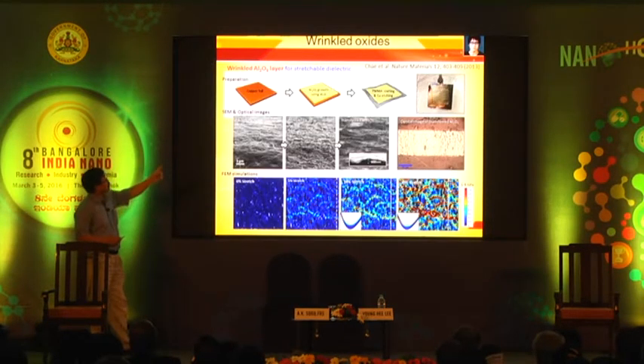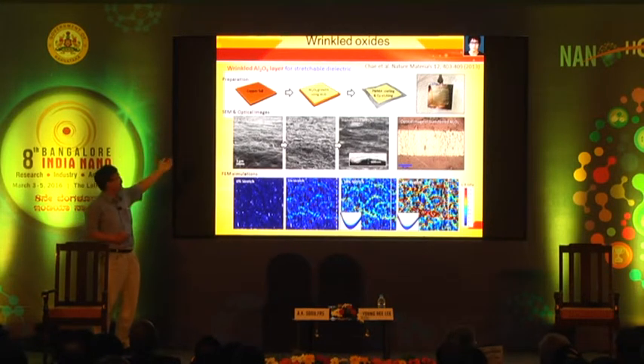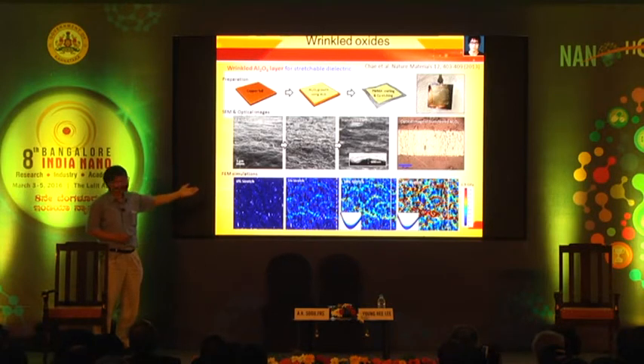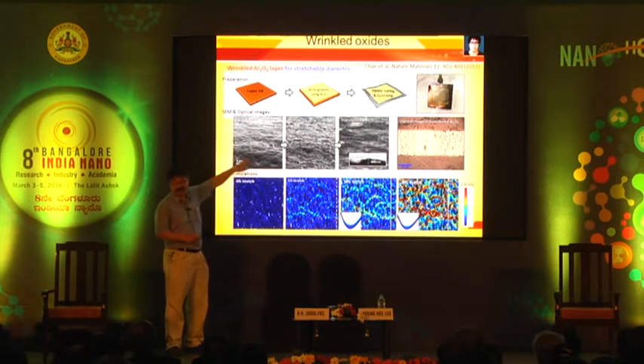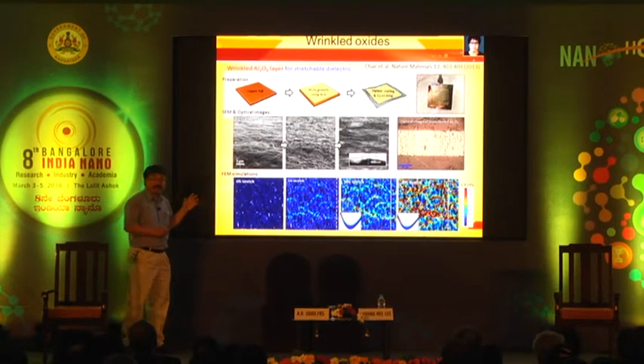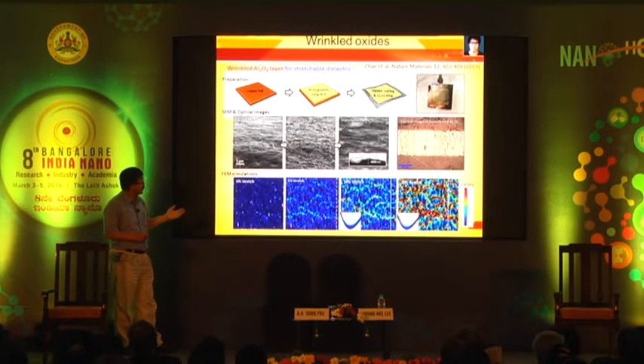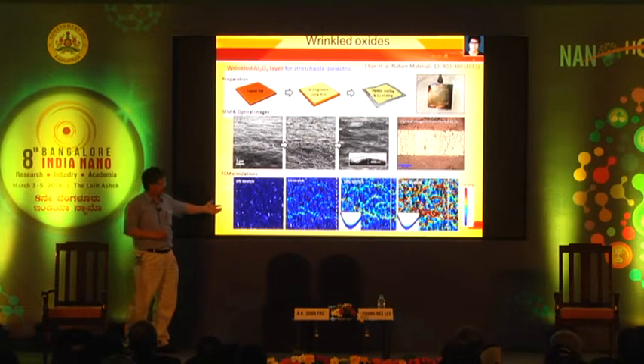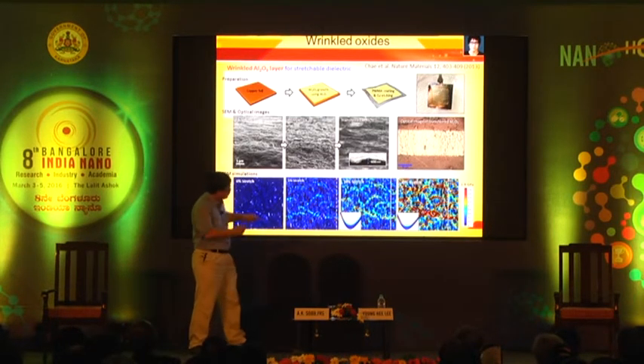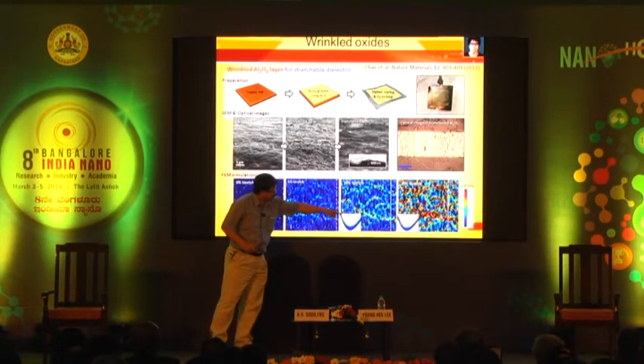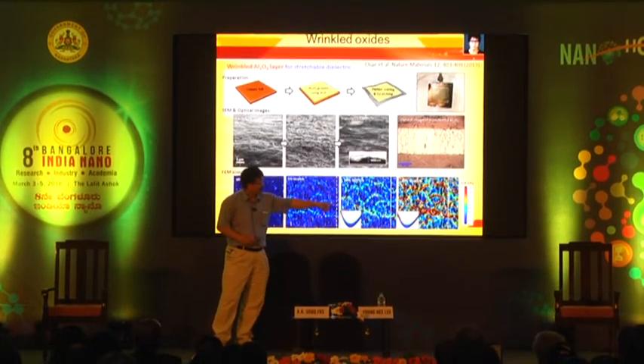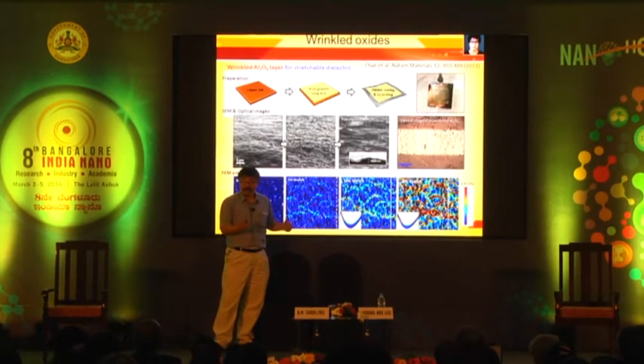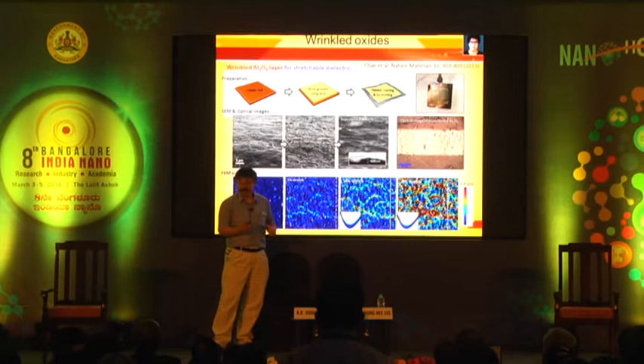So this is the method. We have a copper foil, and we simply deposit aluminum oxide using ALD. Then we deposit PMMA on top of it and remove the copper. And then we transfer this onto the desired substrate. And you can see the wrinkle structure. Then we were still wondering what happens to this, so we did some simulation. You can see when you try to stretch the inner part up to 20%, it is fragmented. The red color means fragmented, but the bottom still maintains the blue color.